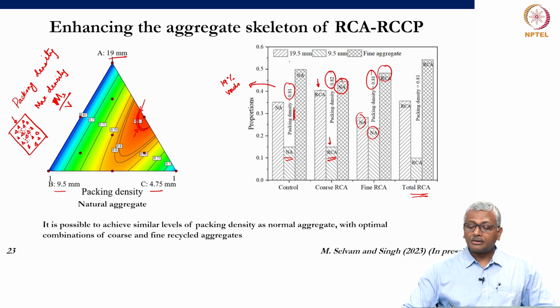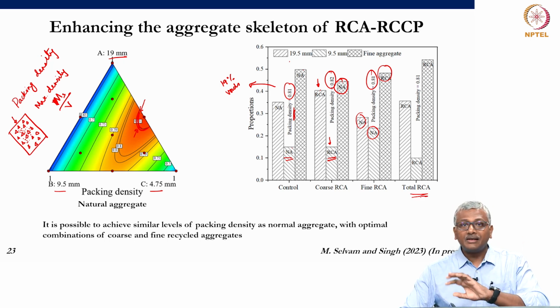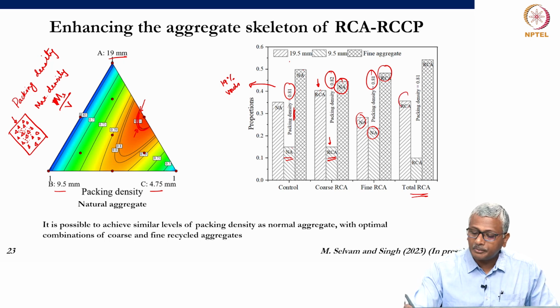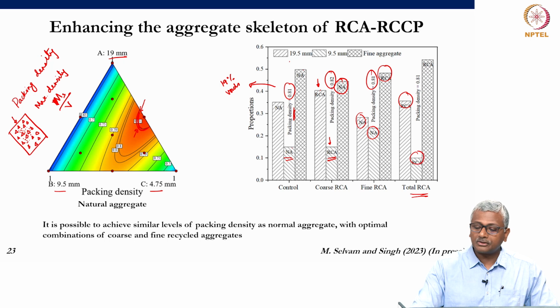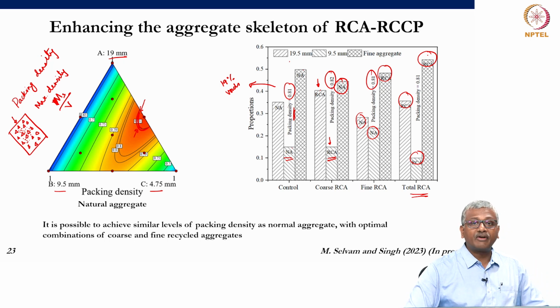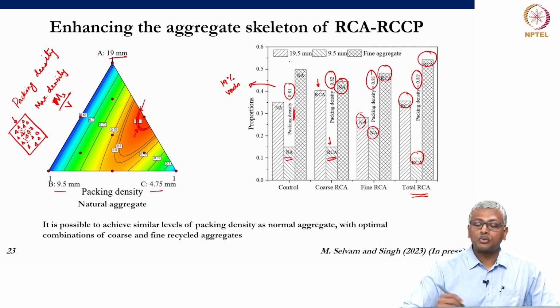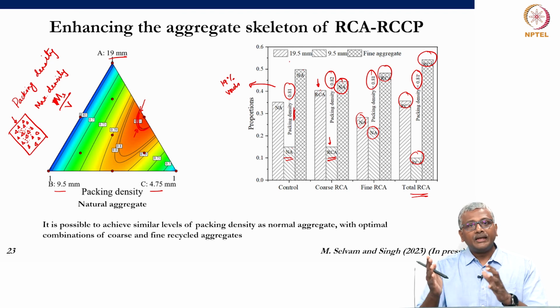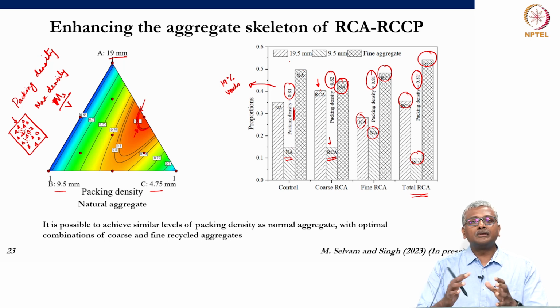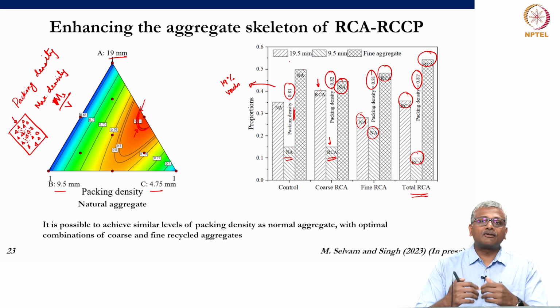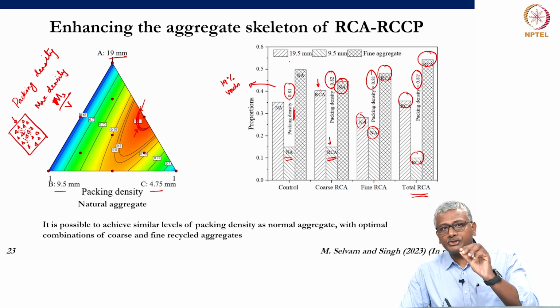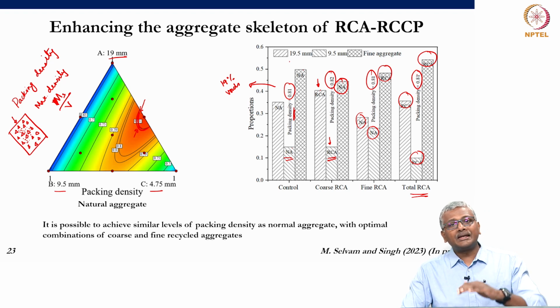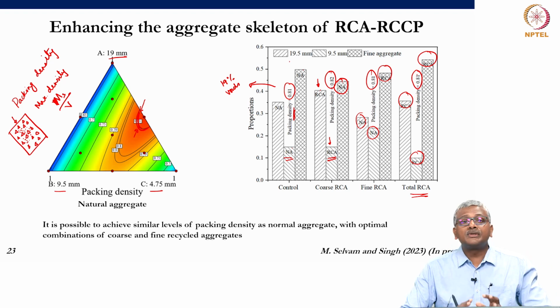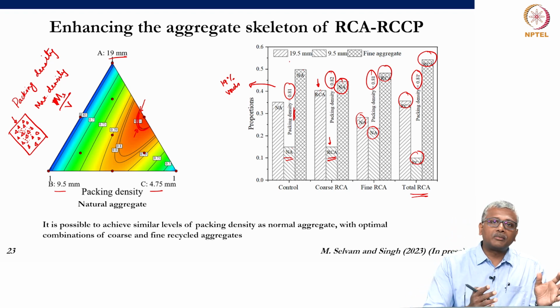Similarly, both coarse and fine aggregate in the last case were from recycled sources. So, here again at 35% of 19.5 mm, 10% of 9.5 mm and 55% of fine aggregate, you are able to now get the same packing density of 0.81. What does this tell you? This tells you that if I design my roller compacted concrete pavements with mixtures of coarse and fine aggregates that are from recycled sources, depending on an optimal choice of the blending proportions, I can then find a way to actually compact these to the same density as I would compact a normal aggregate mixture, okay.